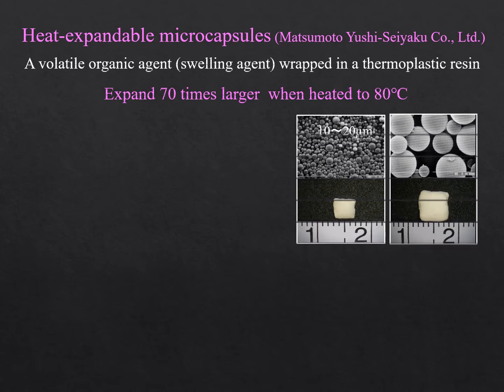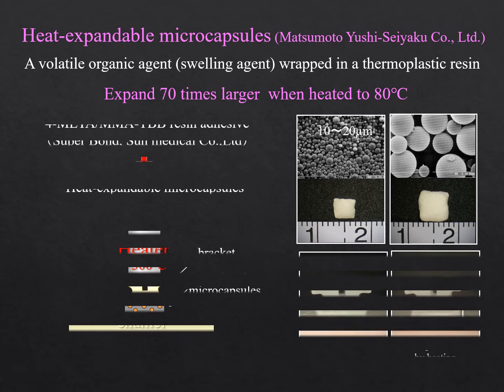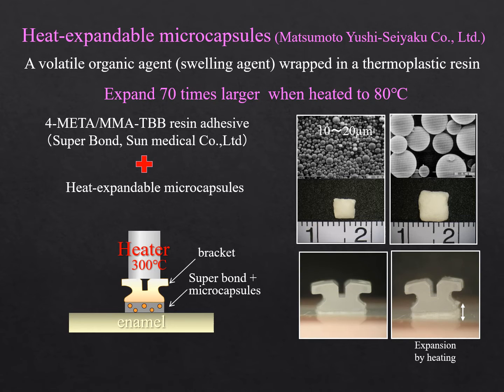We started to study adhesive that could easily remove the bracket after treatment, and we focused on the heat-expandable microcapsules, as shown in the slide. The size of the microcapsules is 10 to 20 micrometers, and they expand 70 times larger when heated to 80 degrees Celsius. At first, we examined a prototype of MMA-TBB resin adhesive, which is a chemically polymerized orthodontic adhesive, and the product name is Super-Bond, containing a certain amount of the microcapsules.